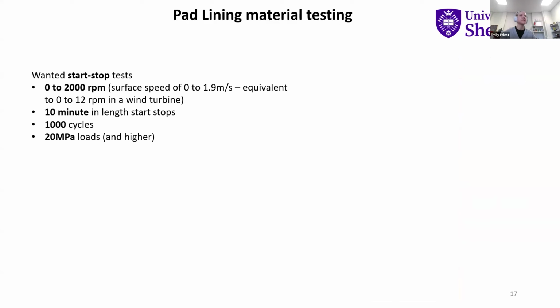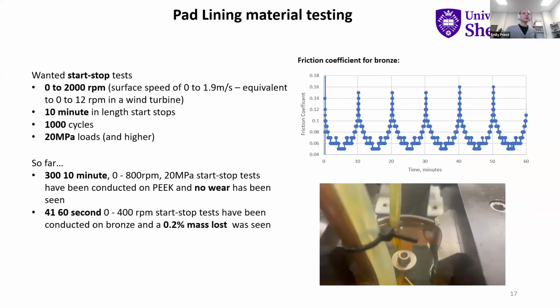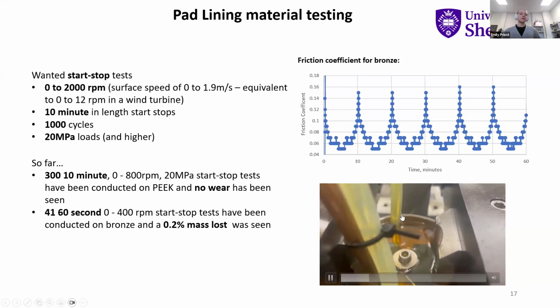So the testing we've completed so far. What we wanted to do, based off studies, was some 0 to 2000 RPM start-stops with 10-minute length start-stops, 1000 cycles and 20 megapascal loads, but probably go higher too. But so far we've just conducted some 300 10-minute start-stops on PEEK, and we haven't seen any wear. We've gone from 0 to 800 RPM and 20 megapascals. And you can see just to the right here a little video of our start-stops for the PEEK.